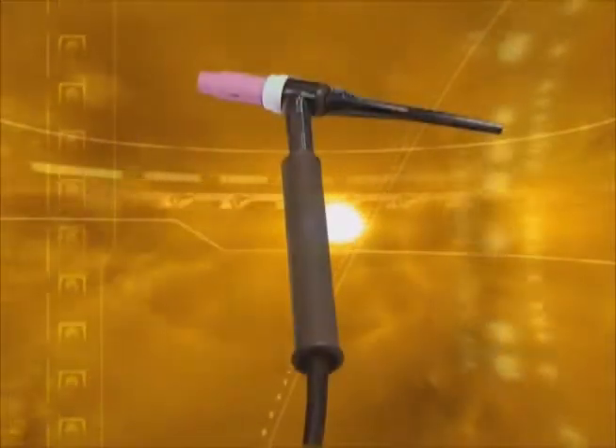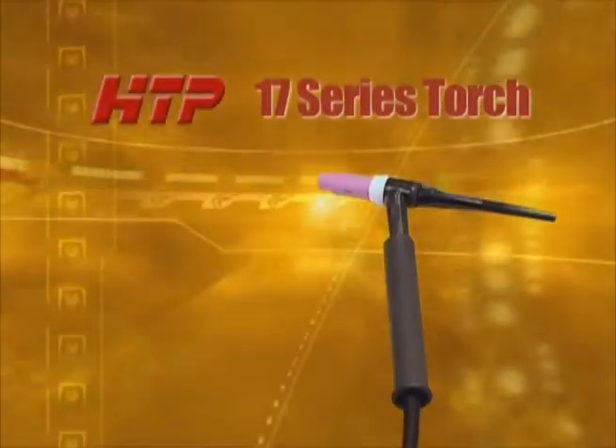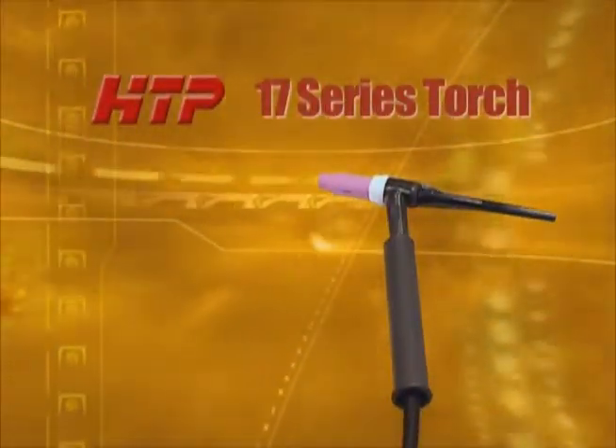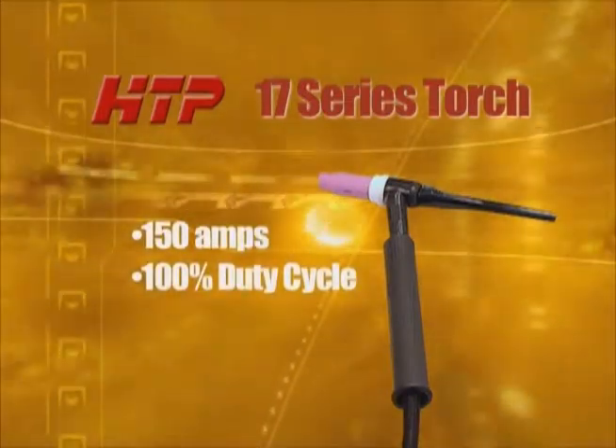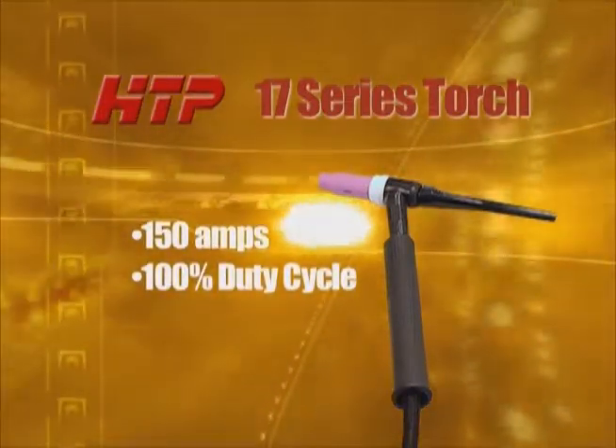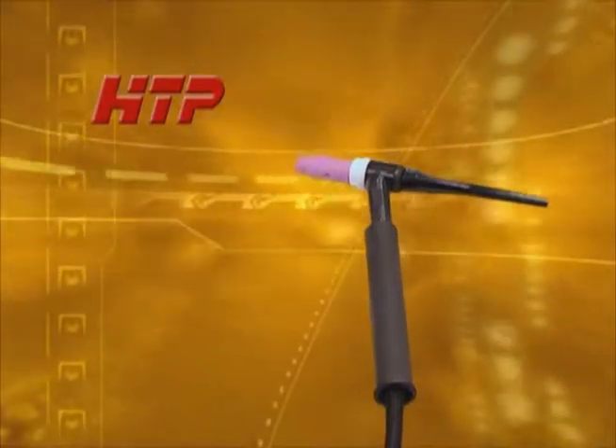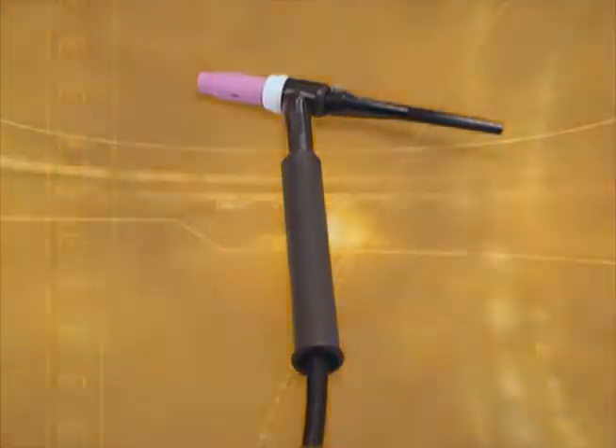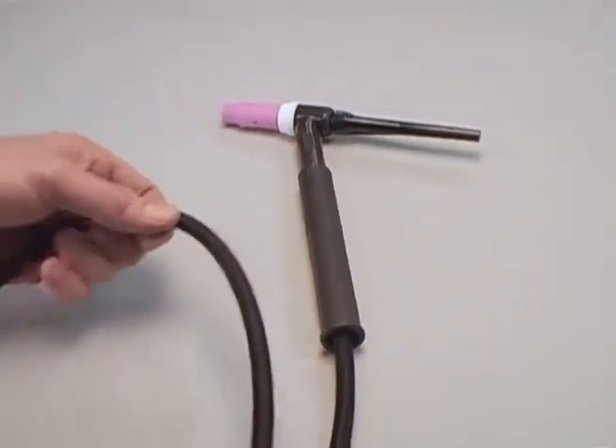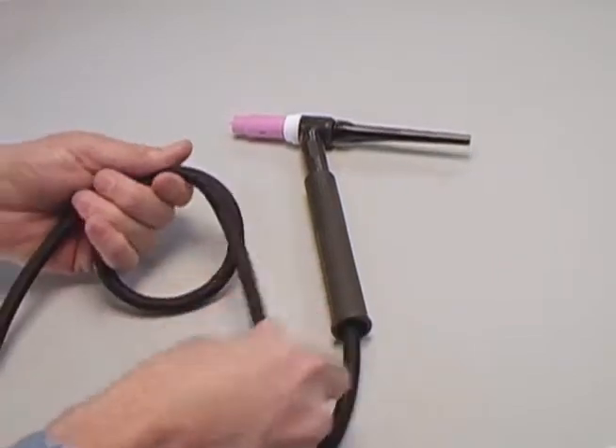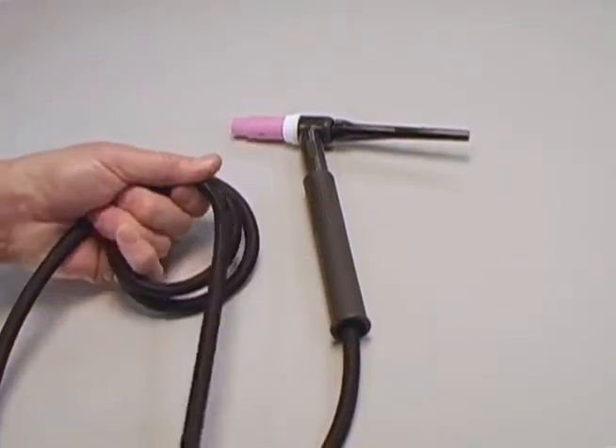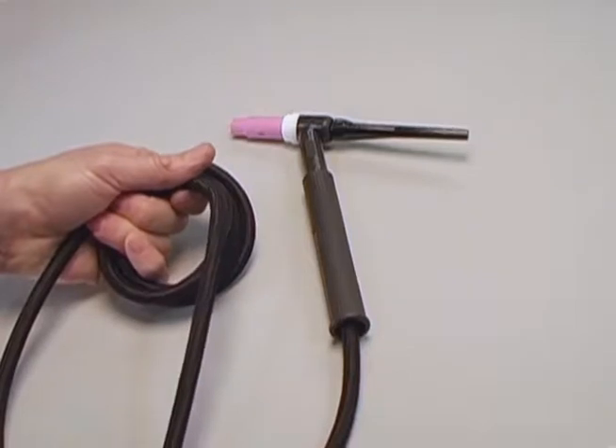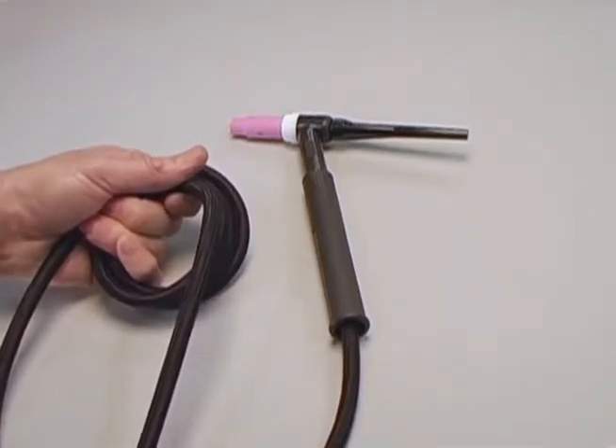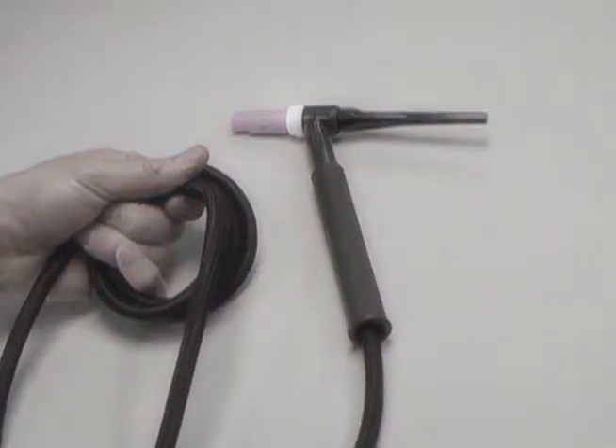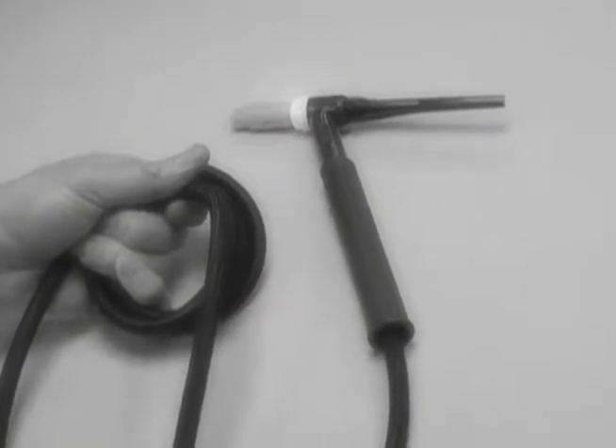One of the most common TIG torches is the 17 series shown here. This torch is rated at 150 amps with a 100% duty cycle. All HTP air-cooled torches feature a single cable design with very flexible cables. Compare this to a separate gas and power cable or a more rigid vinyl cable. The highly flexible cable design makes your welding easier and reduces hand fatigue.